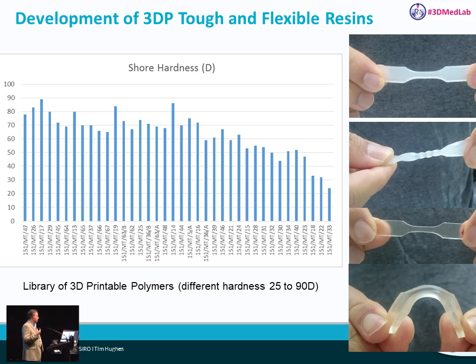We're also able to test the hardness of materials and make a wide range of hardnesses from 25 to 90D. And at the stiff end, they're still quite stiff, but can be bent without breaking. At the more flexible end, down this end, they're very soft and you can bend them multiple times without breaking, and they're elastic, so they return back to the natural state when you let go.